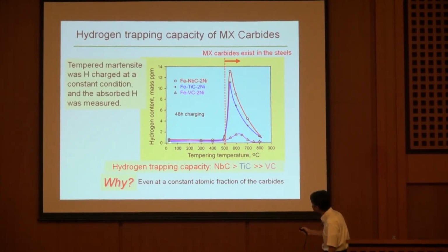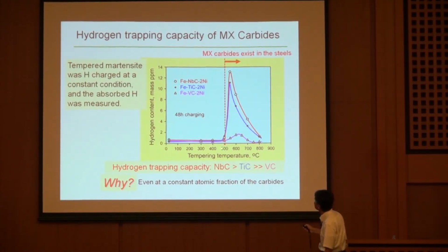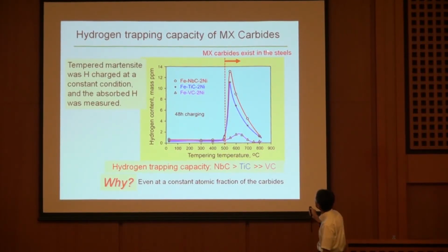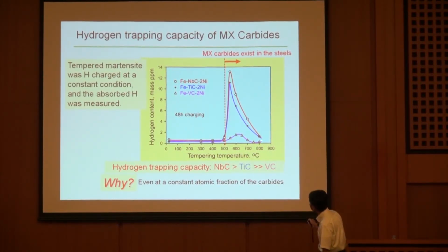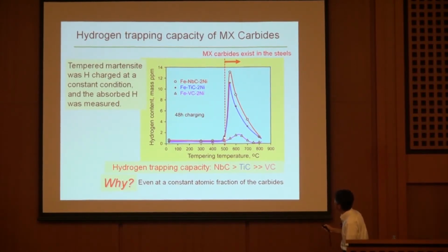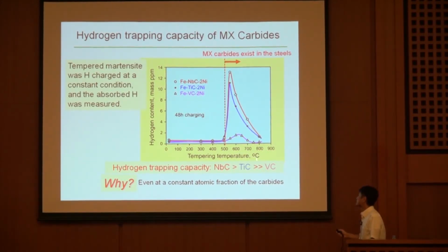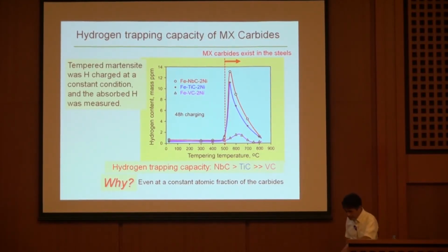The absorbed hydrogen is almost zero when the tempering temperature is lower than 500 degrees C, where the MX carbide does not form. But when the MX carbide exists in the steel, this hydrogen concentration goes up like this, then decreases again like this. And the peak level of hydrogen trapping capacity is the highest in niobium carbide, then titanium, and the smallest in the case of vanadium carbide. So the question arises, why? Even at a constant atomic fraction of carbide, this kind of difference in hydrogen trapping capacity has been observed.